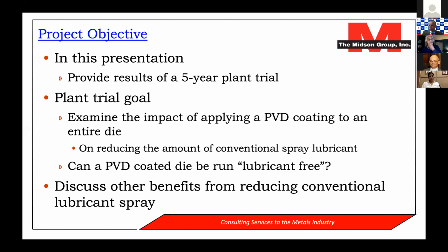In the presentation, as the chairman said, I'm going to be providing some results of a 5-year plant trial that's been going on in the US. The goal of the trial was to examine the impact of applying a PVD coating to an entire die. Any part of the die that was contacted by the liquid aluminum, we put a PVD coating on. So I'm not talking about just coating small cores or small inserts, but essentially the whole die. The goal was, could we apply PVD coatings and reduce the amount of conventional spray lubricant applied to the die? Basically, can a PVD coated die be run lubricant free, with no sprayed lubricant at all? As I'll show later in my presentation, we didn't quite achieve that, but by reducing the amount of lubricant due to the PVD coating, we got a whole range of other benefits that I'll describe later.